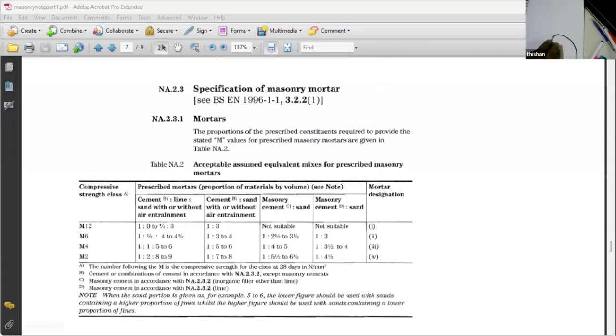So basically M4 means the number following the M is the compressive strength for the class at 28 days in newtons per millimeter square. So when you say M4 mortar, we are looking at a mortar which gives a strength of 4 newtons per millimeter square or 4 megapascal. And to get that, we have to use 1:5 cement sand mix. But the important thing is the cement sand mix should not be mixed in the morning and used in the afternoon. So generally within 2 hours of mixing, the mortar should be used.